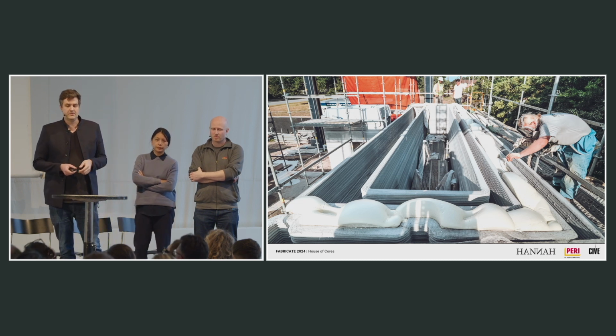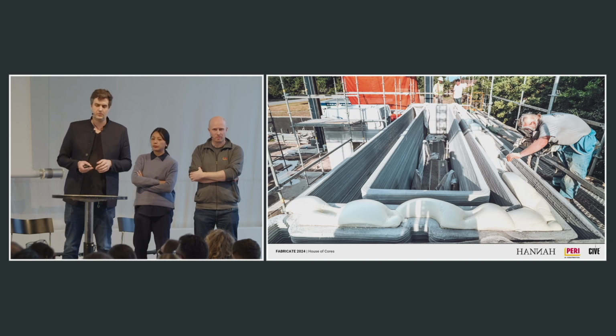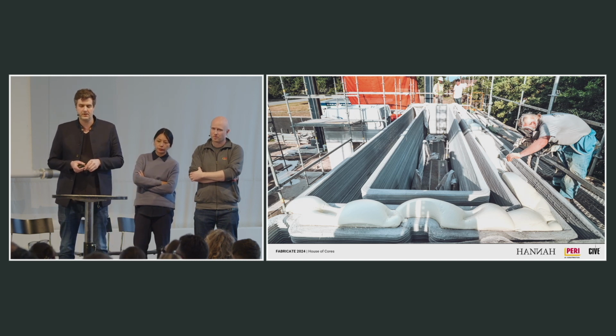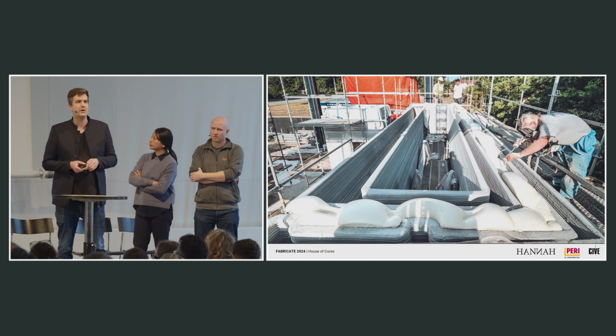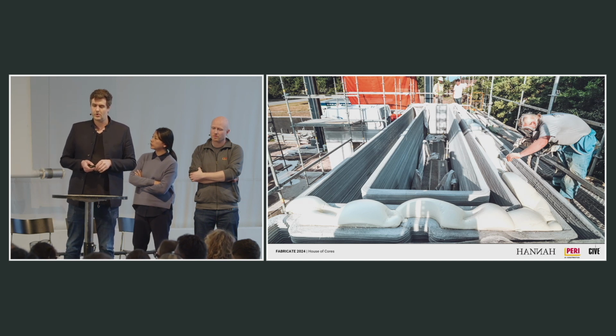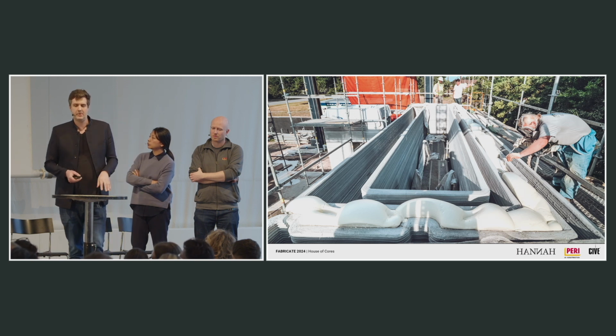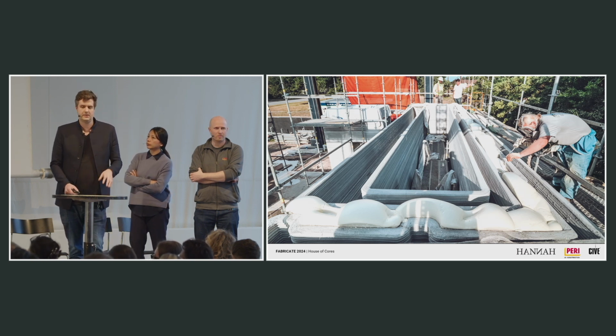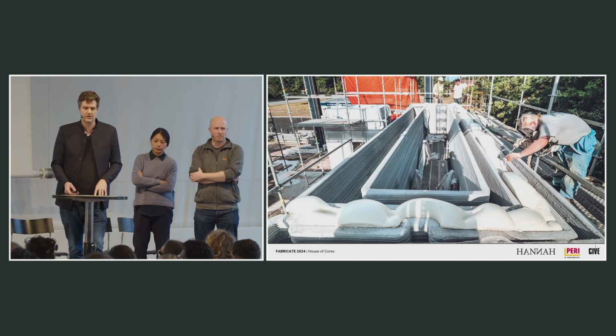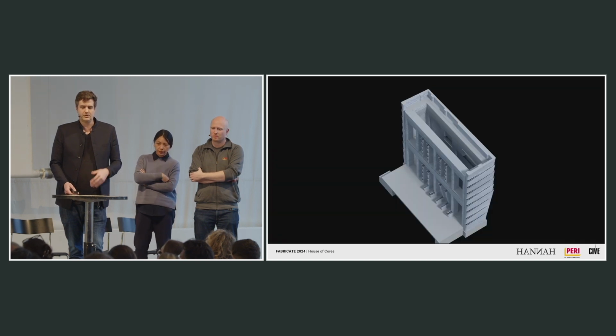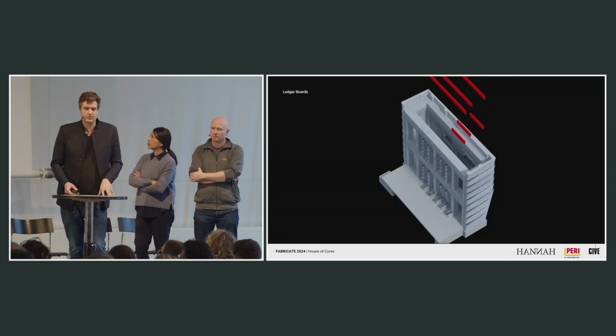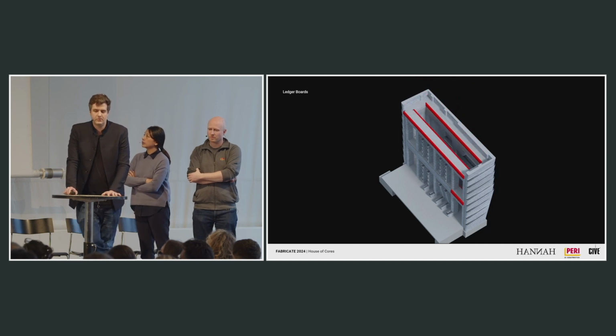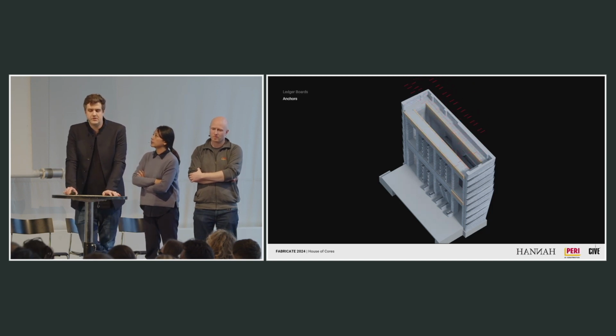The printed walls themselves are insulated using a two-component closed cell foam insulation system with a high recycling content from Huntsman Building Solutions. And that is then paired with an HVAC system to regulate interior temperature and air and moisture content. And so with the cores completed, we are about to start phase 2 of construction, which includes the conventional wood studs and trusses for the floor and roof slabs.